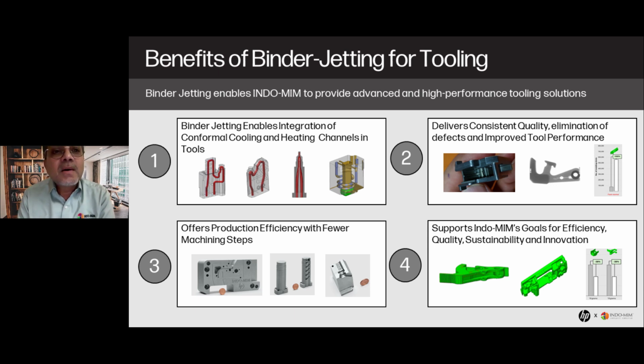Now let me quickly touch base on the benefits of binder jetting for tooling, which are very similar to all the advantages that industry has been enjoying for the last decade through laser bed fusion. So I don't want to spend too much time, but we all know that a 3D printing process allows us to use conformal cooling technology, wherein you can take the cooling channels very, very close to the molding surface, which means you can cool the part or heat the mold elements during the molding process more efficiently. That solved a lot of other issues, and as we move along, I will bring you up to speed on the advantages we experienced because of conformal cooling. We were able to solve a lot of sink issues and a lot of distortion issues. We can get to more of those details.